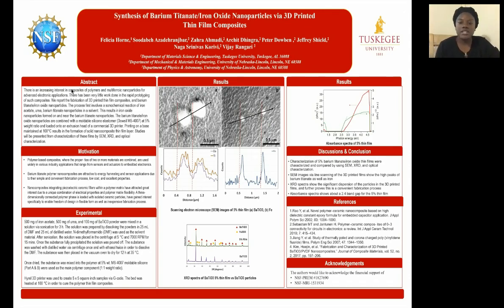Now, also with this thin film, we were able to do optical characterization, which was the absorbance spectra for that thin film. And from that, we just found out that we indeed did have a 2.4 band gap, and that goes along with that iron oxide and that barium titanate within that silicone matrix of my polymer of that thin film. So again, with this work, we were able to characterize through SEM, XRD, and absorbance that multiferroic nanoparticle, the nanoparticles of barium titanate and iron oxide within that thin film composite.